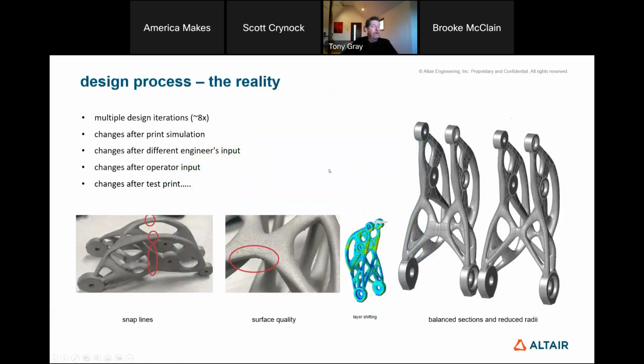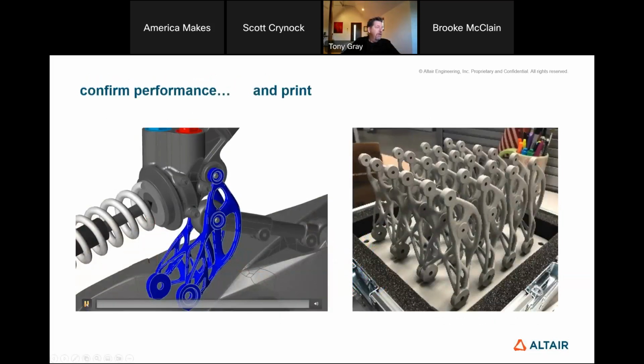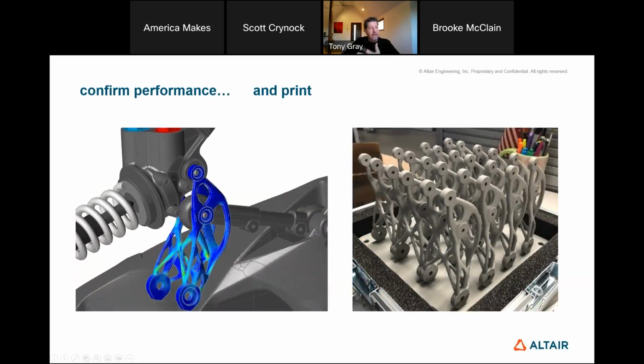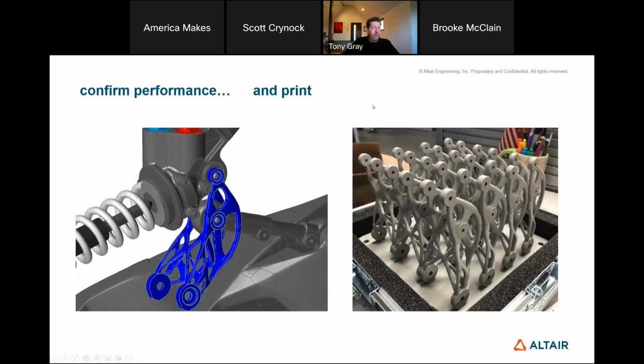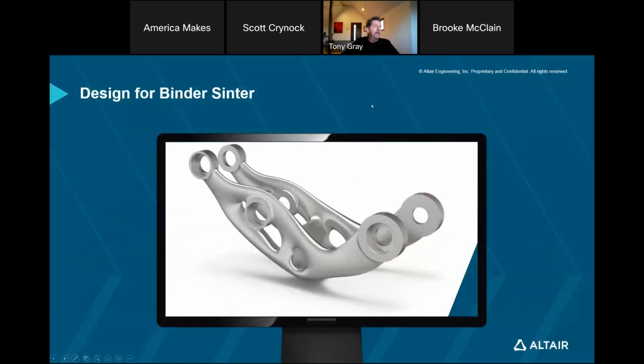And in the real world, we printed this with Renishaw. We went through about 8 design iterations. Partway through, we did some test prints. We saw these snap lines, thought to be due to an unbalanced section, and these quite large radii causing this surface quality issue. So we redesigned it, shifting things around a bit, and in the end got a result that was getting through the print simulation fine. We again confirmed the performance and then printed a bunch of them on a Renishaw printer. So again, a really successful process from start to finish.